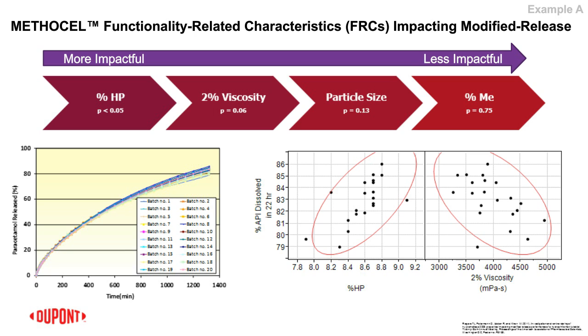But you can see that the relationship between drug release and HP was much more defined, much stronger than the relationship between drug release and 2% viscosity, at least within the regime we're talking about in this study. Now, I have to say, take it with a grain of salt, right? Because if you look at that y-axis, we're only talking about 79 to 86%. So we're really only talking about 6 or 7 percentage points here, right?